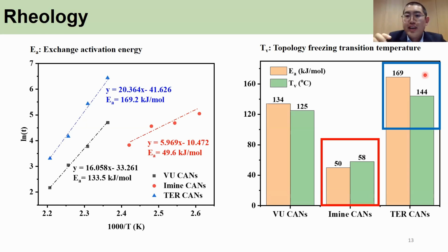Unlike the transesterification in epoxy systems, in our work, we use a ring opening reaction between the anhydride and the fatty alcohol to create networks. At a higher temperature, the ester bonds are catalyzed by the neighboring carboxyl groups, which allow them to reform into the cyclic anhydride structure. Essentially, this is dissociative.